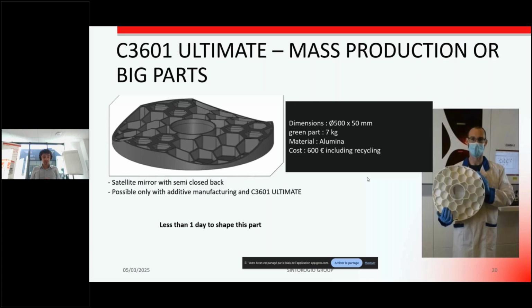The first example of a big part that you can see on this slide for space application is an alumina mirror for satellites. This alumina mirror with a semi-closed back design is only feasible with the additive manufacturing process. As you can see, the size of the part is quite big: 500 millimeters for the diameter and 50 millimeters for the height. And we need 7 kg of slurry in order to print such a part. To give you an idea, the printing time of such a part is less than 1 day. It's 23 hours. Obviously, after that, debinding and sintering still need to be done, but at least you have a rough idea of the printing time.